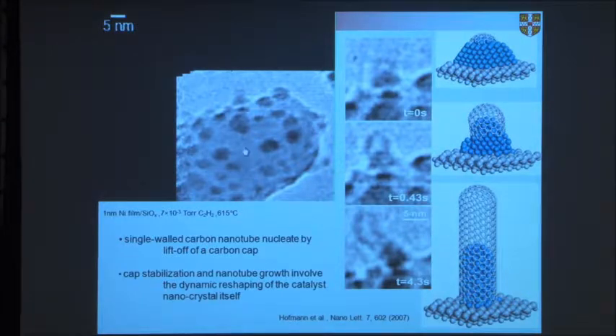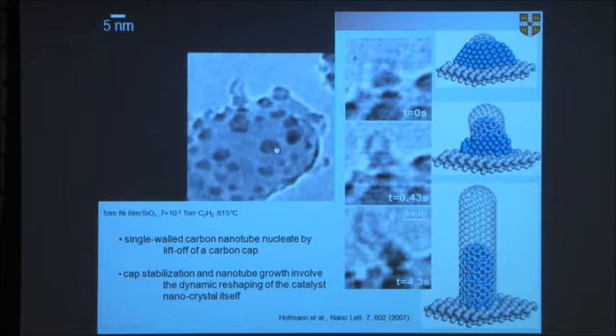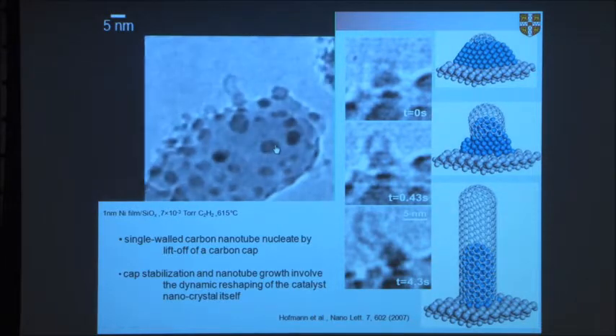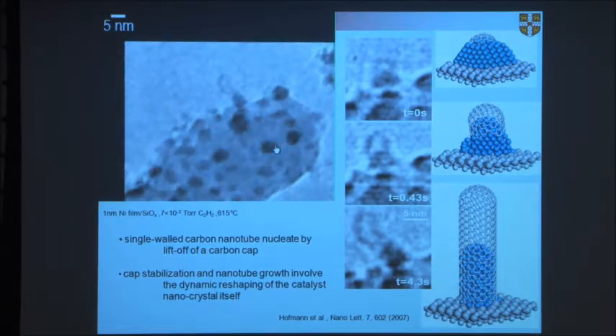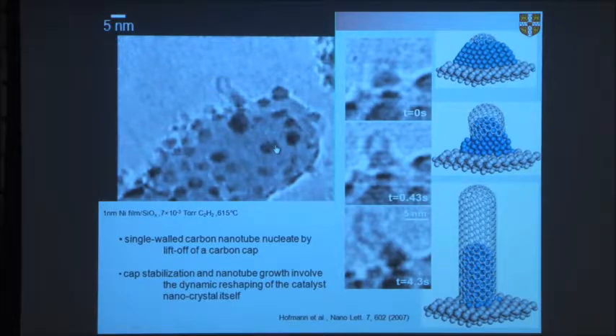If, however, you do the same again, so here's another example. In this case, we've got a much smaller ball, only 1 nanometer of nickel on SiO2. And you might think, look at this one here, exactly the same process, add some carbon-containing gas, what happens to the growth? You would think the nickel would come up and the tube would grow down, but it doesn't. You end up with the nickel staying where it is, and the nanotube growing up.